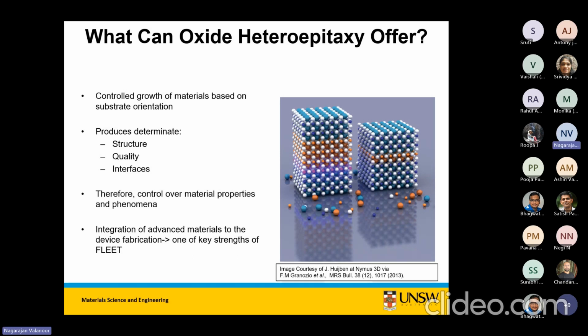You can tailor the structure, and not every system needs to have atomically sharp interfaces. That's the one thing I try to get across. In fact, there are some systems where our goal was to not get atomically sharp interfaces. The classic example is strontium ruthenium oxide, which is an electrode, and then you grow PZT on it. If you grow it very slowly, the titanium from PZT starts to replace ruthenium in strontium ruthenium oxide, because ruthenium oxide evaporates. The strontium ruthenium oxide is an electrode, and the interface, which is this diffused interface, is a semiconductor. And then you have PZT, which is a really good insulator. So there, we don't want atomic level sharpness, but we were able to make buried interfaces by design. So that is something that oxide heteroepitaxy really offers us.